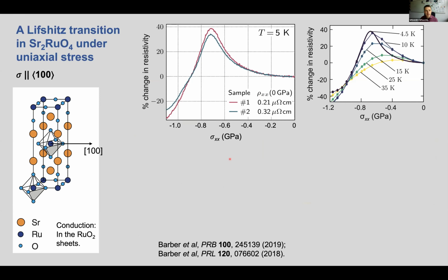Right, and here are some data. So this is the percent change in the resistivity from the unstressed value, starting here at 0 GPa. Negative values of stress denote compression, so we're compressing the sample in this direction, and at about 0.7 GPa, the resistivity of these two samples at 5 Kelvin is enhanced by almost 40% from the resistivity of unstressed strontium ruthenate. So there's a much, much stronger response than in the conventional metals, rhenium and aluminium.